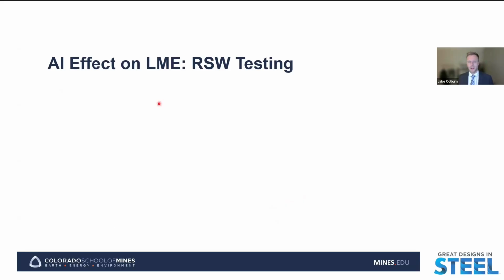So then with that, the next step we wanted was saying, okay, from those conclusions, those results we saw in hot tension testing, will we see similar results in resistance spot weld testing? So the LME testing that we did in resistance spot welding consisted of creating a single square pulse weld at an increasing current through the 6 to 9.5 kiloamp range in 0.5 kiloamp increments with a weld time of 600 milliseconds, which is roughly twice that of what the standard would be for this sheet thickness.